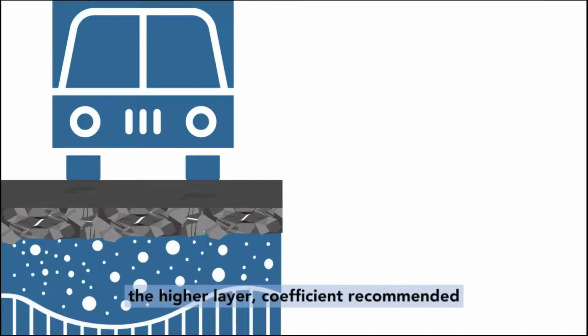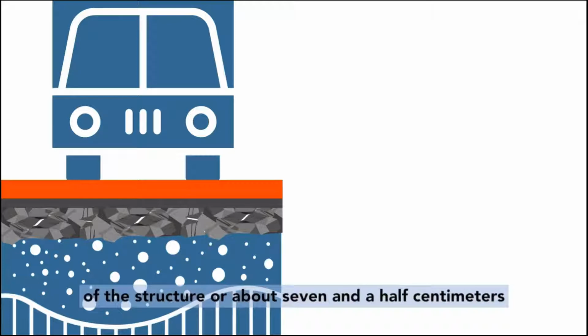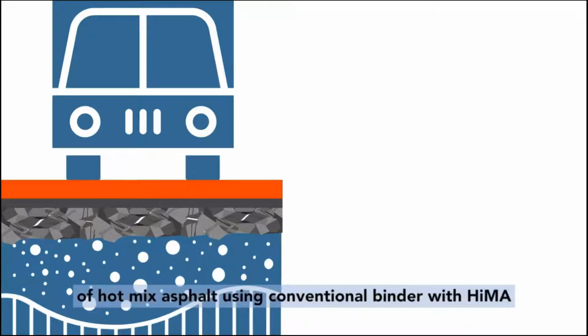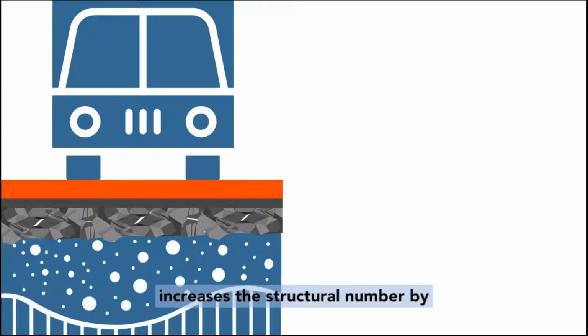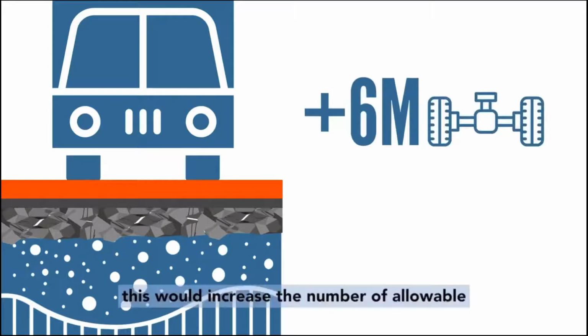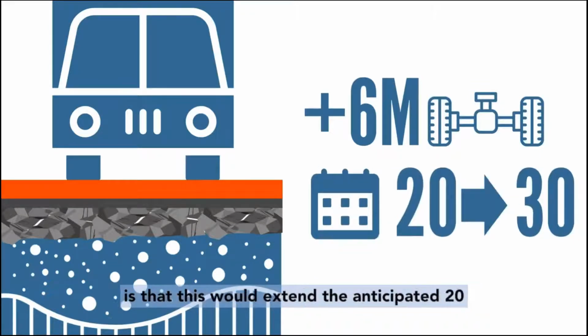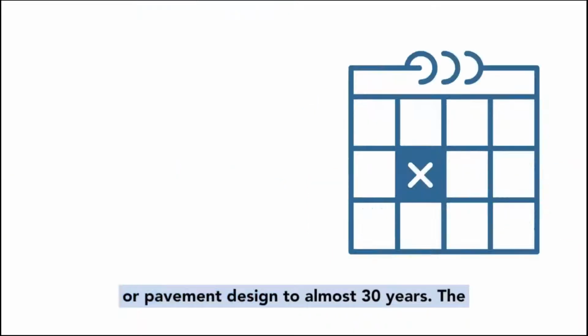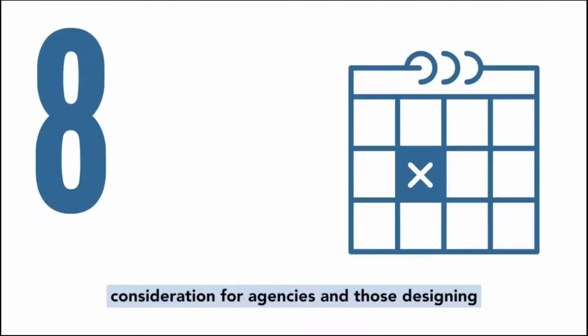Using the higher layer coefficient recommended when using HiMA, replacing 3 inches of the structure, or about 7.5 centimeters of hot mix asphalt using conventional binder with HiMA, increases the structural number by 0.30. For the assumed design conditions, this would increase the number of allowable ESALs by almost 6 million while maintaining the same thickness. Another way to look at this is that this would extend the anticipated 20-year pavement design to almost 30 years. The extended performance life is an important consideration for agencies and those designing pavement structures to take into